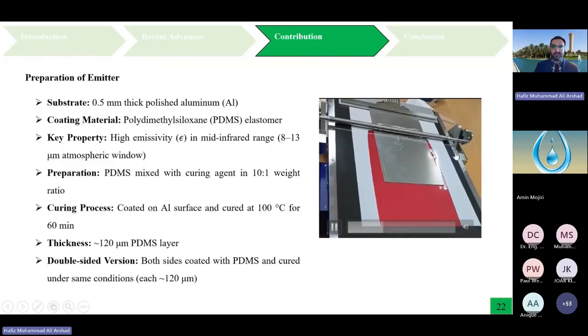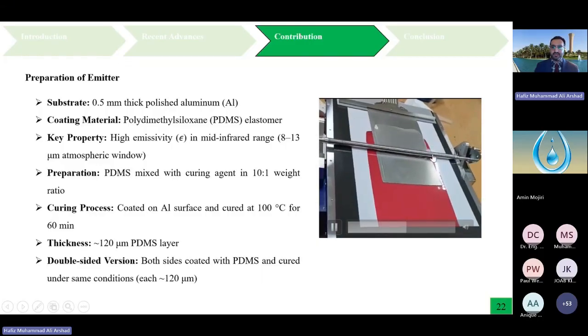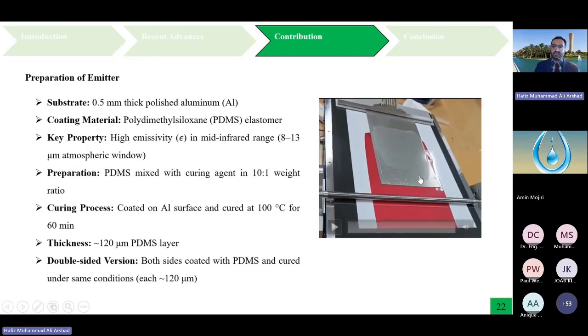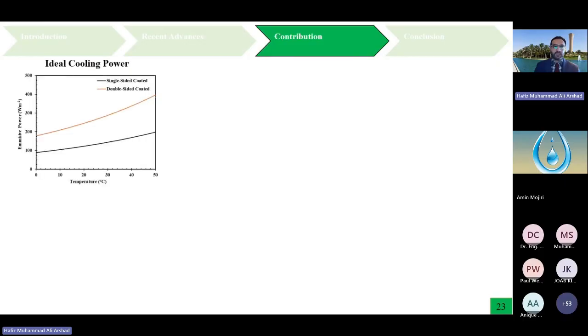This is a mixture of PDMS with curing agent, and with this coater we may achieve this coating as shown in the video. So what is the ideal emissive power? It depends on the temperature. For example, if we have an ambient temperature around 30 degrees C, the maximum emissive power that we can achieve is up to 120 watt per meter square. If we have a double-sided coating, this could double the power, up to 240 watt per meter square.